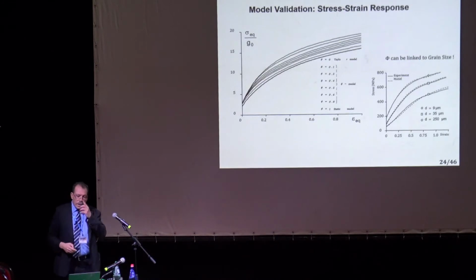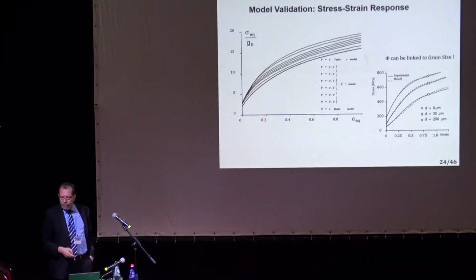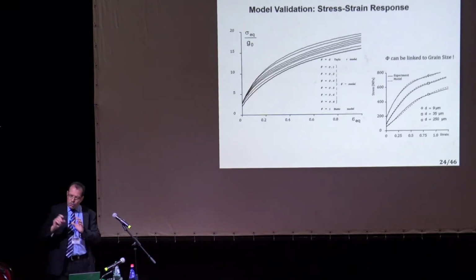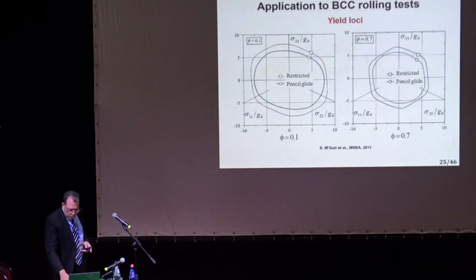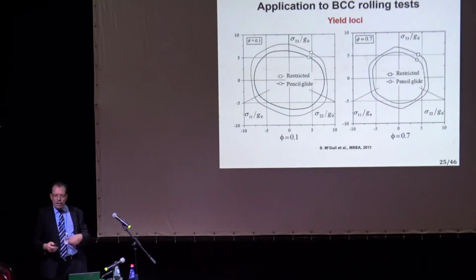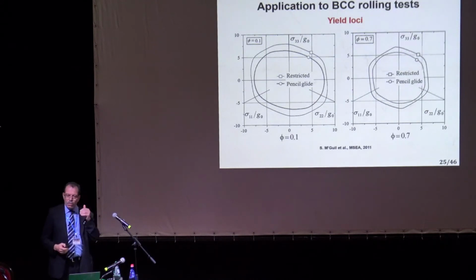So the story here is to tell you that phi could be linked to stacking fault energy, that I mentioned in the beginning of the material, but could also be linked to grain size. So we can maybe link it to the Hall-Petch effect and so on. But we did not go that far. I mean, we are hoping to get some metallurgists to help us maybe link this phi to these microstructural features, could be grain size, stacking fault energy, and so on. We also applied it to many other materials. First results are for FCC, but we also applied it for BCC. We also applied it for HCP, but I'm not going to show all of these results.